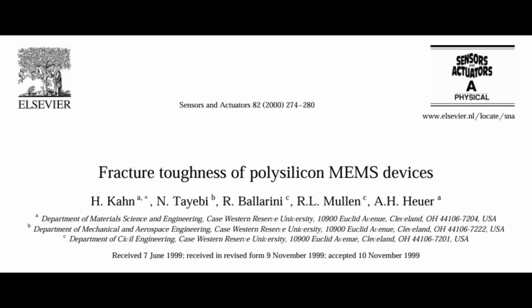This creates small radial cracks extending outwards from the corners of the indent. Okay, but pressing something hard like that into a thin film must create a lot of internal stress, right? Wouldn't that mess things up? Absolutely, and that's where a really crucial step comes in. Annealing. They heated the samples up to 1,000 degrees Celsius. Wow, really hot. Why? That high temperature bake is essential to relieve the residual stresses that get locked into the material during that indentation process. Makes sense. Relax the material.